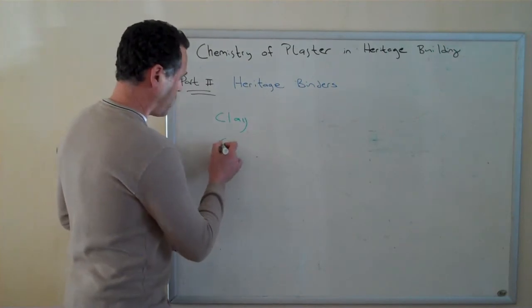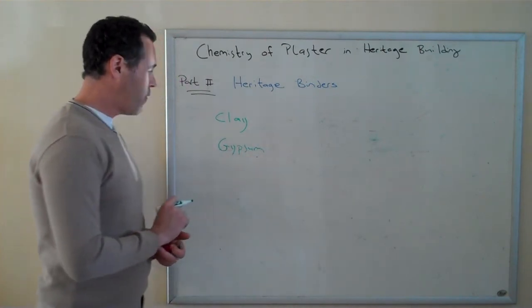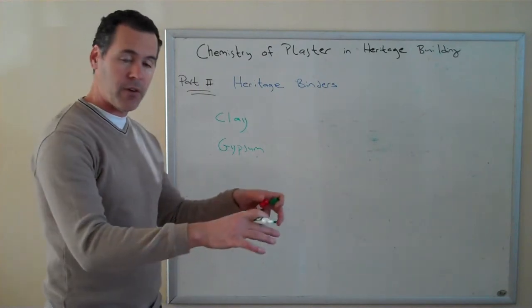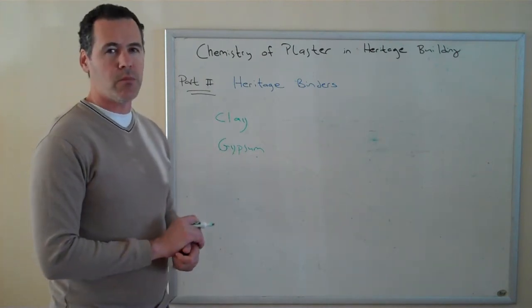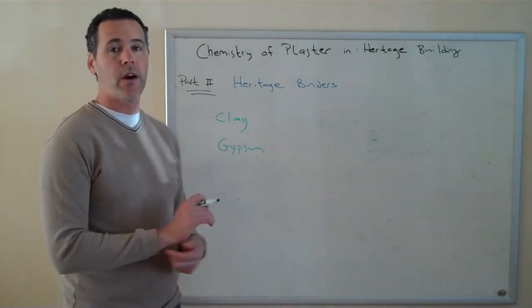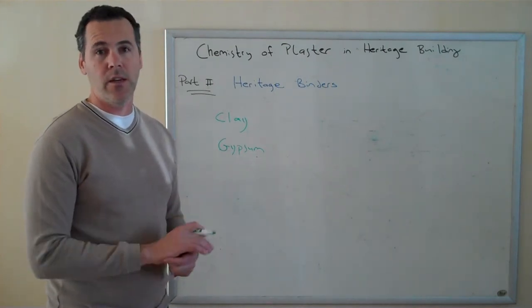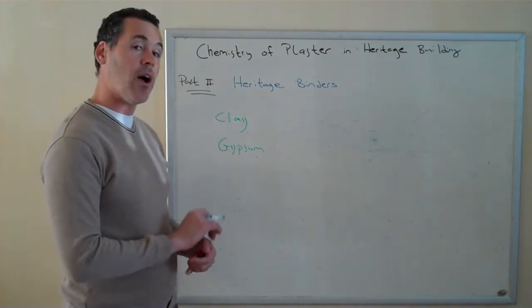The next plaster perhaps discovered is gypsum. Gypsum was likely discovered as a plaster next because it has a very low cooking temperature. Gypsum rocks found around a fire would, at 350 degrees Fahrenheit, begin to calcine — losing a percentage of their water. If water were then thrown on the fire to quench it, that gypsum would fall to powder, and excess water would create a putty that hardens. No doubt, when man first discovered that, he found those rocks might be pretty useful.